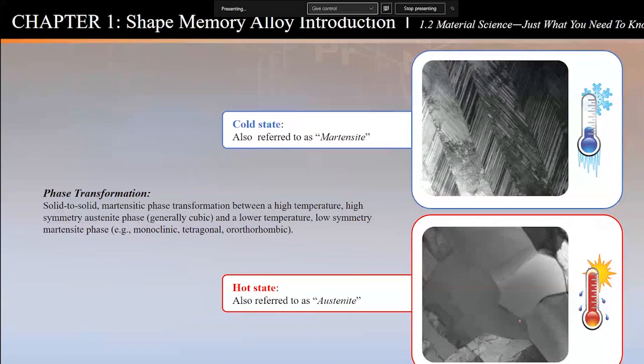And this is done at a microscopic level, but the end result, if you take a component, because this little grain is going to here and the next one is going to here, you have a macroscopic deformation that is reversible, controlled by temperature or load or some other stimulus. So hopefully this gives you a good idea of what shape memory alloy from a microstructure level looks like, what's the terminology used to describe shape memory alloys, the austenite, martensite, and why it is reversible.